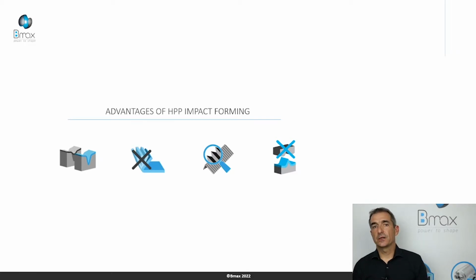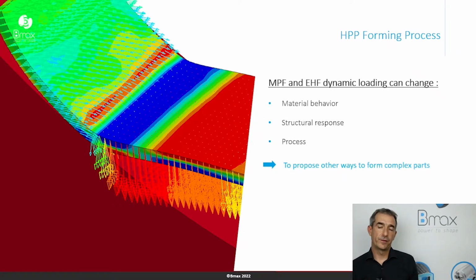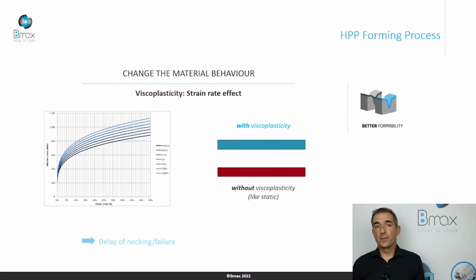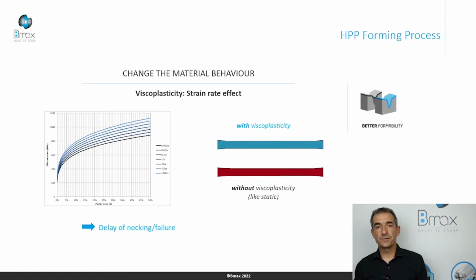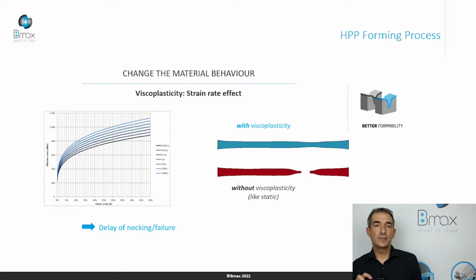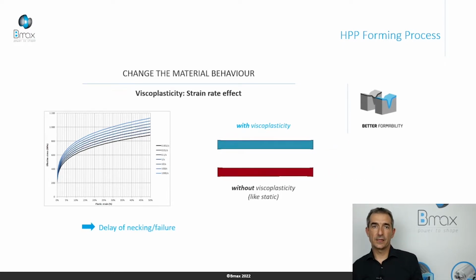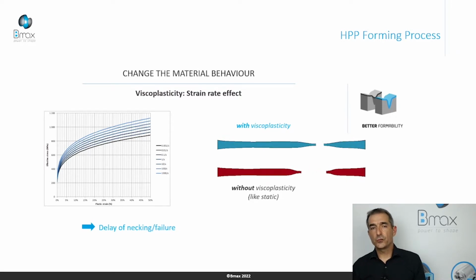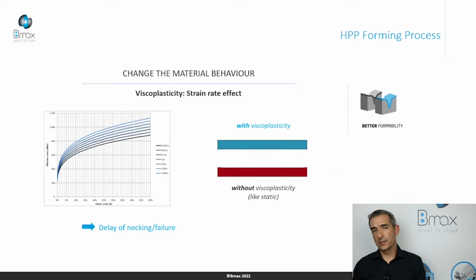What are the main advantages of impact forming, like MPF and EHF? MPF and EHF deliver dynamic mechanical loading, and it can change material behavior, the structural response, and the process itself. So these processes can propose other ways to form complex parts. First, the materials. Some materials have a stiffness which depends on the speed of loading. If we generate a high speed of deformation, high strain rate, we can increase the stiffness of the material. It's viscoplasticity. Viscoplasticity usually can delay the necking, the critical thinning, and the crack.